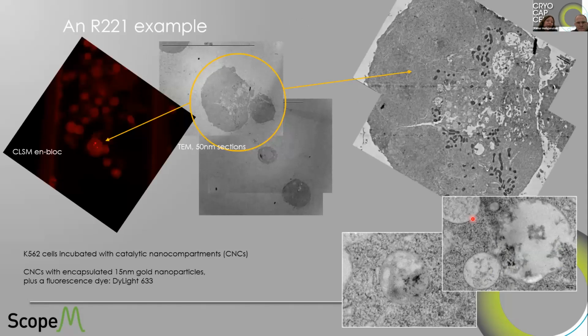Now, Xavier already mentioned the R221 resin, which was specifically designed by CryoCapsule to maintain fluorescence in these resin samples. And this is my very first experience with R221. And you see it's not perfectly preserved here. We have the cell here. High pressure freezing didn't go well that day, but still, you see we have some fluorescent spots in the cell here. We find it again in the TEM section, and it was about these vesicles where we wanted to find those nanoparticles, or those nanocompartments, back. So this worked. This was really, as I said, my first trial ever with R221, and it worked on the first trial. So that was a really good experience.